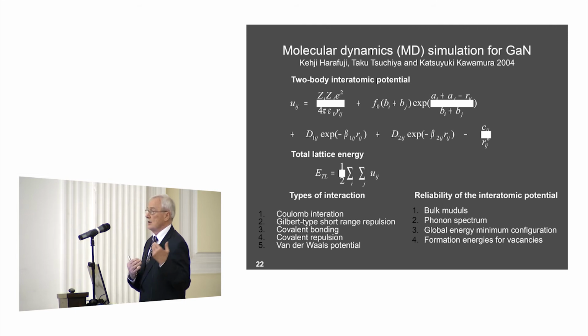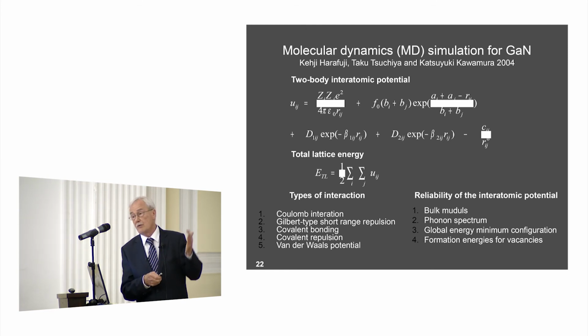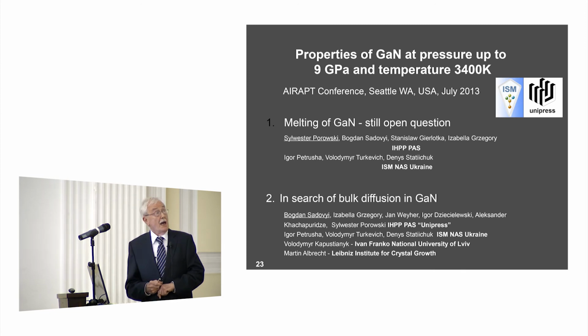However, many of these constants are obtained by ab initio calculations. And the other possibility to increase the reliability of this method is comparison with well established experimental values. And this was done; the constants were adjusted by comparison with bulk modulus, phonon spectrum, global energy minimum configuration, and formation energies for vacancies. And what I would really like now is to convince you that this molecular dynamics theory describes the data which we obtained much better than the Van Vechten theory, which was accepted up to now.